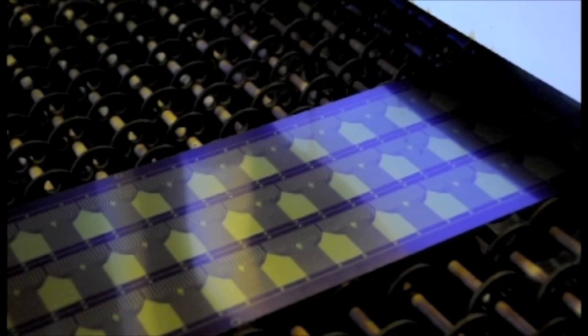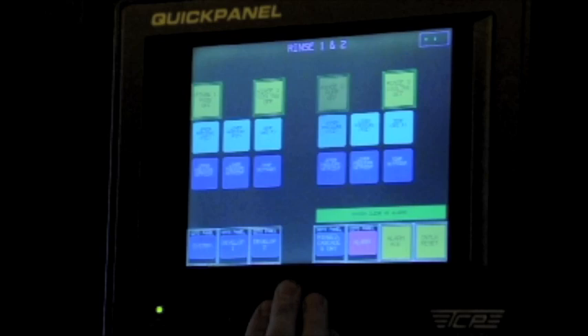After printing, unpolymerized photoresist is selectively removed and base metal is exposed in an operation known as developing. The PLC-controlled developer is a conveyorized machine that sprays a proprietary solution that effectively removes unpolymerized photoresist.